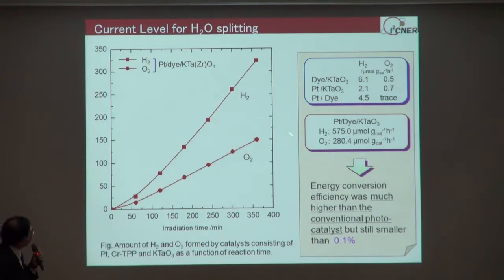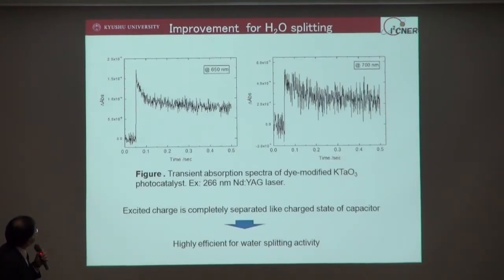ratio to the water. But unfortunately, on these systems, the energy conversion efficiency was much higher than the conventional photocatalyst, but still smaller than 0.1%. This 0.1% includes the irradiation. But anyway, this conversion efficiency is much smaller than the solar cells. But we found a very interesting result.